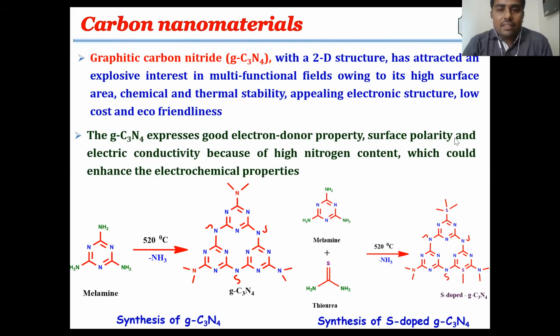Graphitic carbon nitride with a 2D structure has attracted an explosive interest in multifunctional fields owing to its high surface area, chemical and thermal stability, appealing electronic structure, low cost, and eco-friendliness. The graphitic carbon nitride expresses good electron donor property, surface polarity, and electronic conductivity because of high nitrogen content, which will enhance the electrochemical properties.